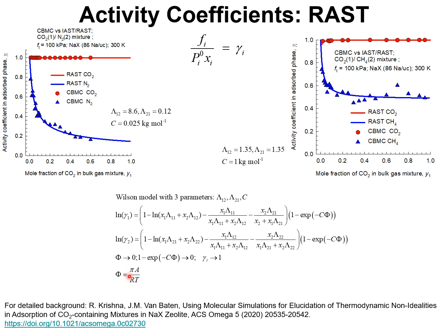For vanishingly small values of the surface potential, the activity coefficients of both components must tend to unity, and therefore the parameter c ensures that the limiting behavior is observed. I'll return to this limiting behavior in the next slide.